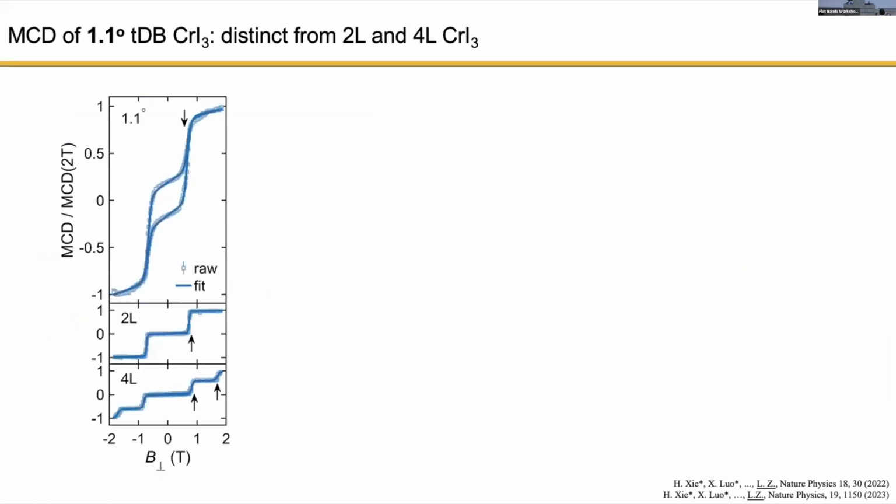So then we do our optical measurements. The optical measurement was introduced by Professor Xiaodong Xu in the previous talk, which is magnetic circular dichroism, which measures the reflectivity difference between left and right-handed circularly polarized light. Typically we consider this signal to be proportional to the magnetization of the system. But recall that we were dealing with a bilayer on top of a bilayer. If we do homogeneous stacking, we wouldn't expect any magnetization in such a system.